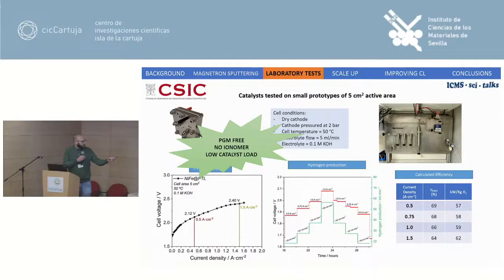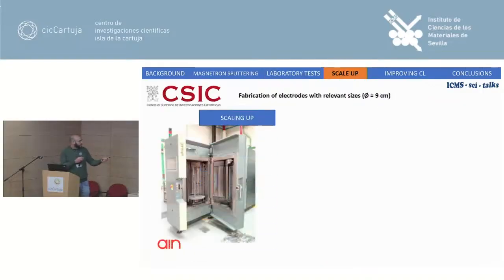And this efficiency translates into a specific power consumption of more or less 60 kilowatt-hours per kilogram of hydrogen produced. If we use about 0.14 euros per kilowatt-hour, this indicates that our hydrogen costs around 6 to 9 euros to produce 1 kilogram of hydrogen. So at this point, with the development performed by Esther and Celia and the measurements that we did in